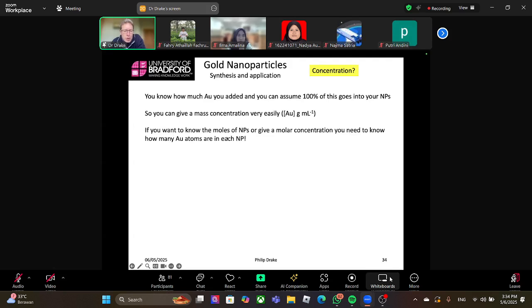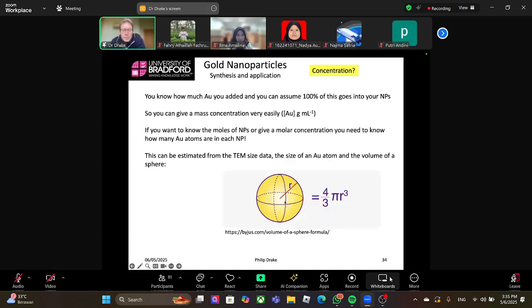If you want to know the molar concentration, you need to know how many gold atoms are in your nanoparticles. You need to know the average size of your particles. You can estimate this from TEM or from UV-Vis spectrum. If we know the size, we can work out the volume of a sphere. So once you know a diameter or a radius, you can work out the volume of a nanoparticle, 4/3 pi